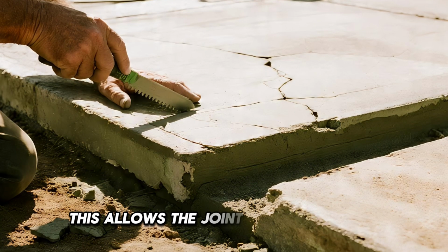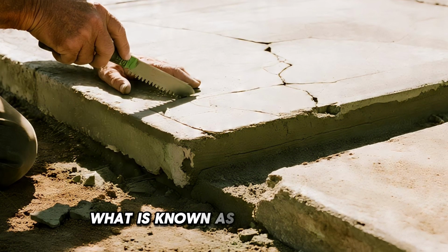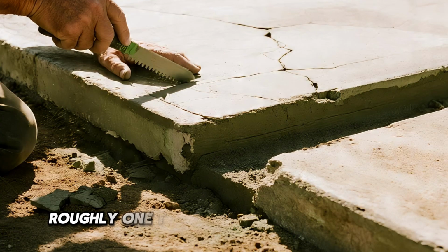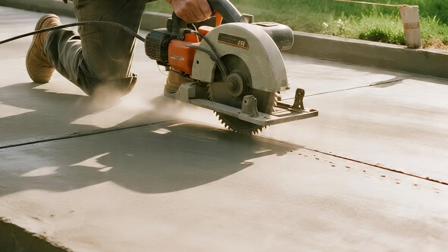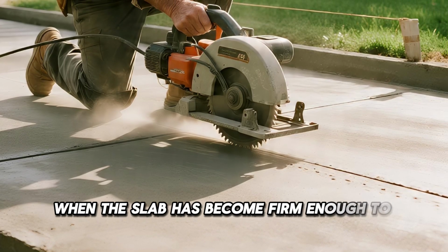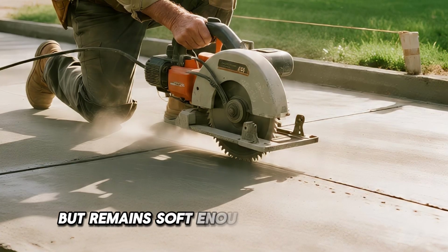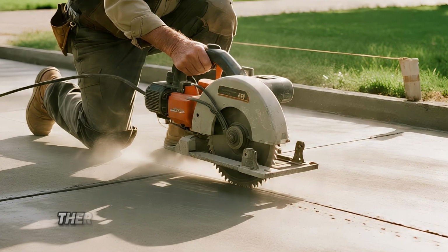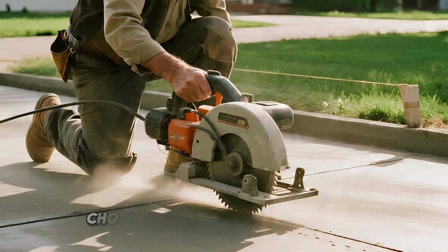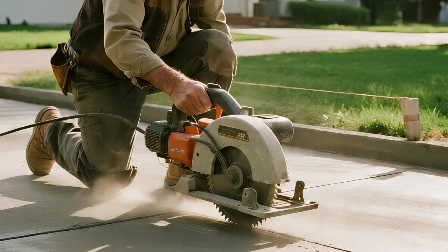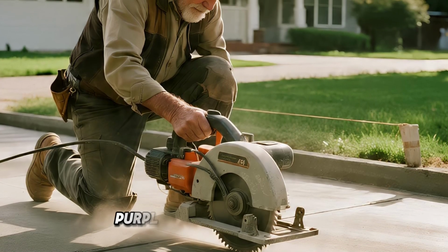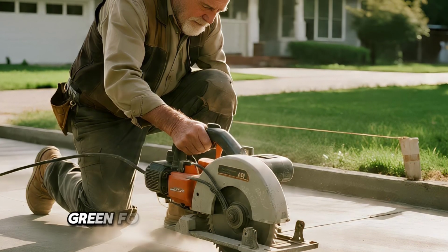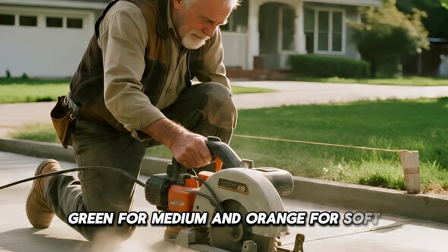This allows the joint to be cut during what is known as the green zone, roughly 1 to 3 hours after finishing, when the slab has become firm enough to walk on, but remains soft enough for a clean cut. When operating a Soft-Cut saw, there are several professional practices worth following. First, choose the correct blade color. Soft-Cut blades are color-coded according to aggregate hardness: purple for hard aggregate, green for medium, and orange for soft.